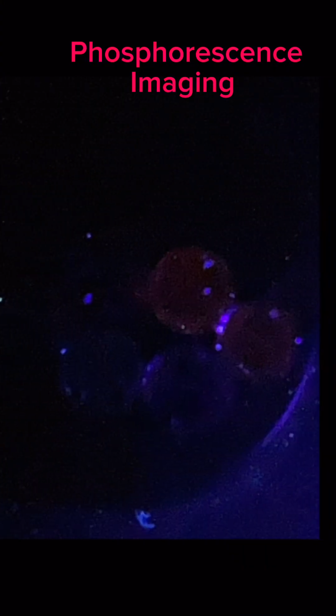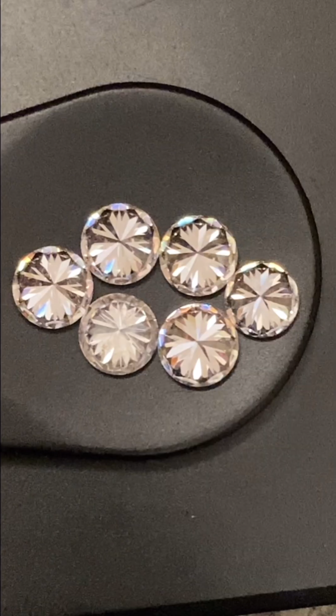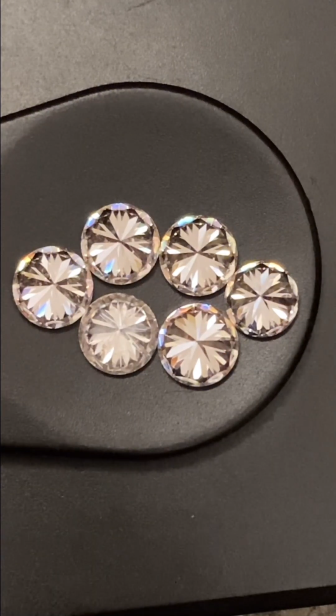What's very interesting from this demonstration is that all the stones that strongly phosphoresced and the stones that also fluoresced, which was the teal green fluorescent stone, didn't have any electrical conductivity results under the conductometer.